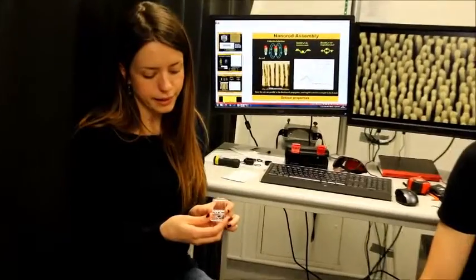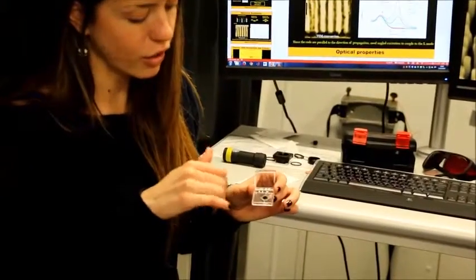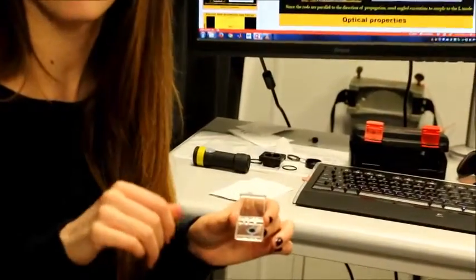It's possible to see how the color is a reddish color. And this is due to the fact that these gold nanorods are interacting as a collective entity and not as an individual, not as a gold film or as an individual particle that would look more yellow.